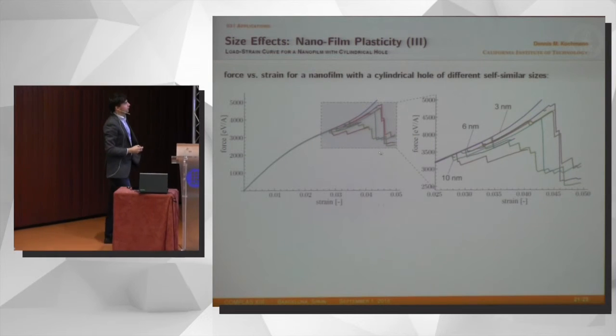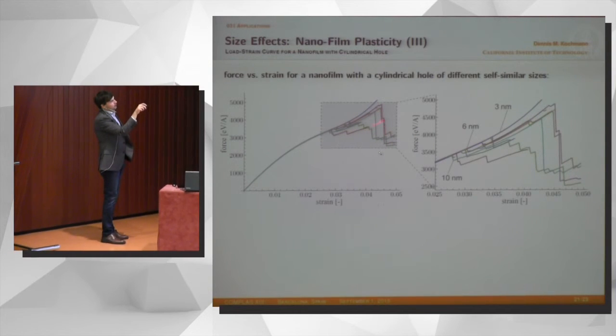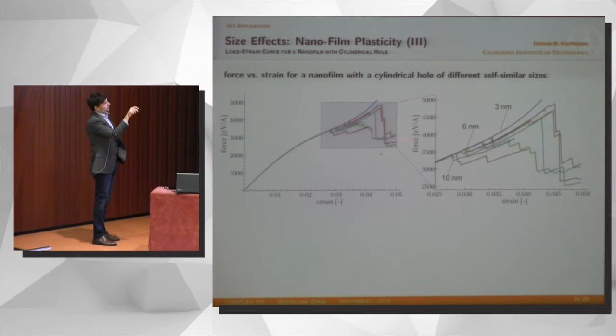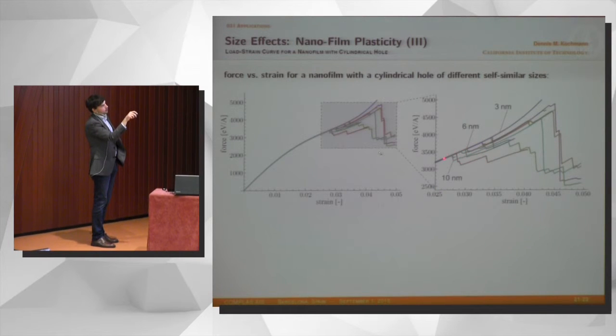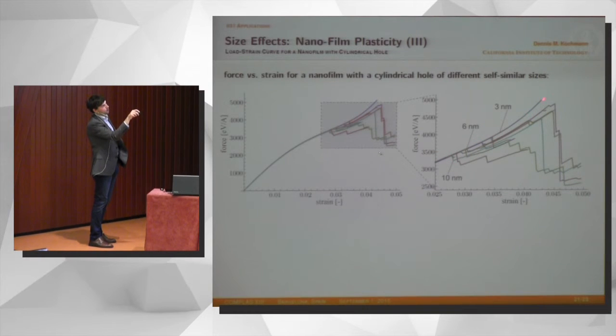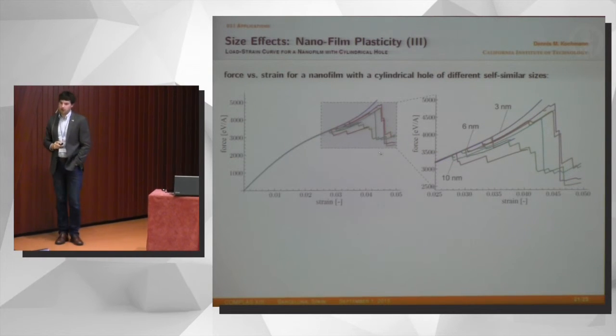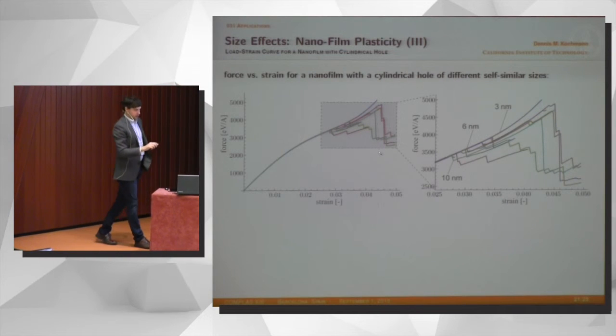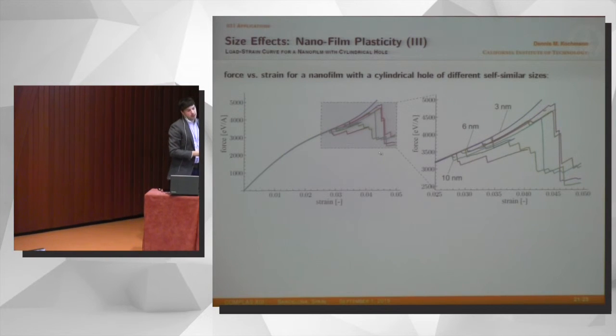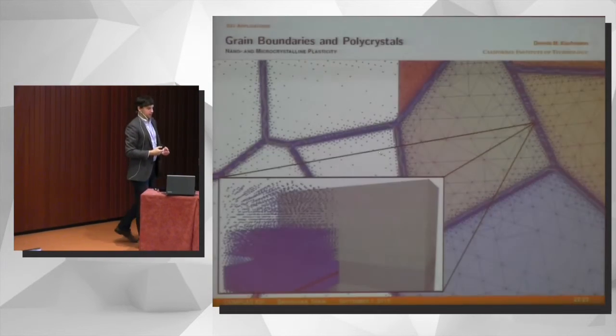If you look at the stress-strain or force-displacement curve, it looks generally like this, first elastic, then inelastic behavior. And you can see that the biggest hole shows plastic loading and dislocation onset very early on, whereas the smaller holes just behave elastically for a long time before they eventually start to show dislocation activity. So again, that's a size effect we can beautifully capture.